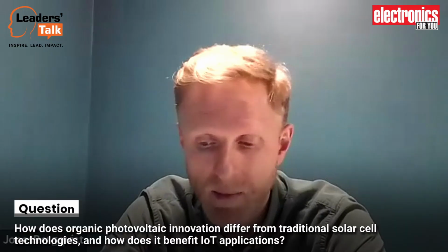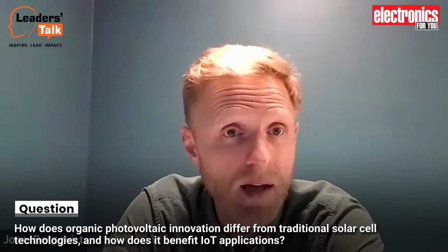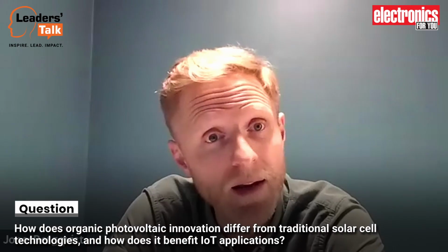How the innovation benefits IoT applications is that you have a new technology where we see that we have a really high and robust performance. And if you look at indoor applications for IoT products, typically the light intensity varies quite a lot. So if you know that you can trust the minimum performance of your solar cell, then the only thing you need to consider is the light intensity variations, depending on where you place your sample, for instance. Other aspects of our solar cell that I think can be beneficial is that they are really low weight. The total thickness is 0.2 millimeters or 200 micron. They have a quite low environmental impact comparably, and are lightweight and fairly easy to integrate.